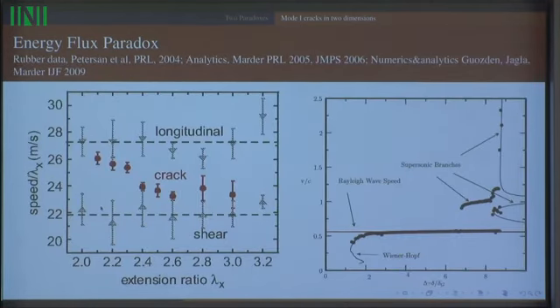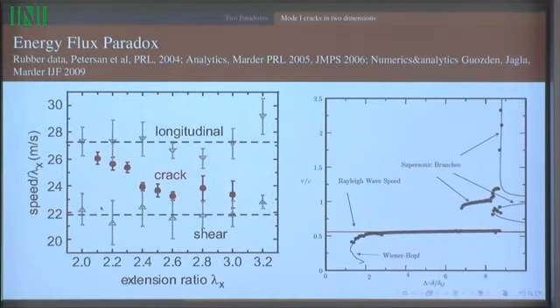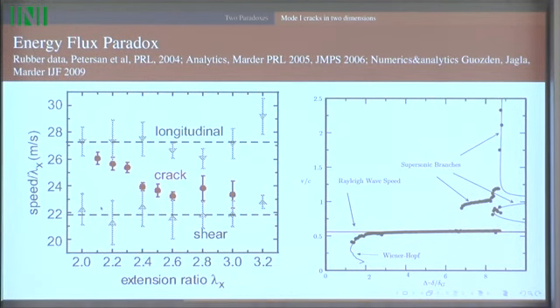But there's experimental and numerical and analytical evidence that supersonic cracks can exist. I first came across this in experiments I did with Robert Deegan, Paul Petersan, and others. They were experiments in rubber, so you might worry about whether there's something weird particular to rubber, but these were crack speeds. These were the shear and longitudinal speeds in the material. I think Ares Rosakis has measured such cracks in plexiglass. Jay Fineberg has found them in gel. So I think the experimental evidence at this point is relatively solid.